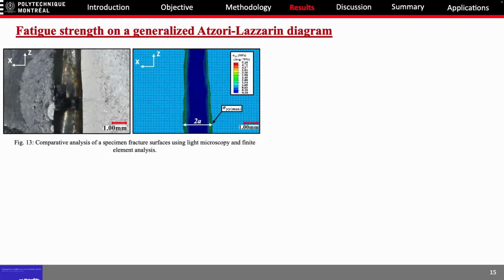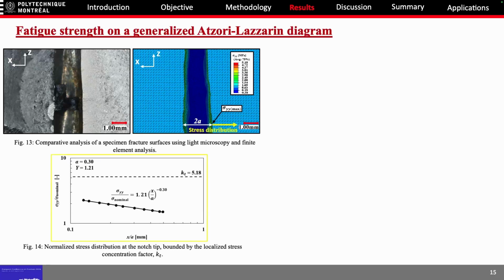So now, the main goal of this project: fatigue strength on a generalized Atzori-Lazzarin diagram. To do so, this is a comparative analysis of the real specimen with the finite element analysis one. 2a represents the discontinuity size at the location where the y direction stress was maximum. From there, we retrieved the stress. We did the stress distribution at this location, and we retrieved essential variables such as the singularity exponent, 0.3 for this specimen for example, the geometry factor, and the stress concentration factor. From there, we can build the Atzori-Lazzarin diagram.